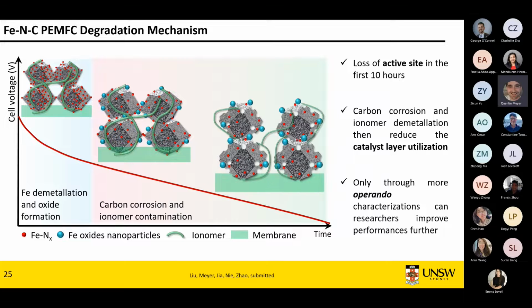Now, the next step, which is basically when you lose most of the performance, what happens is you can see that your carbon has become a lot more porous, so you have large holes. You can imagine this sort of large hole in your structure. You've lost even more active sites.